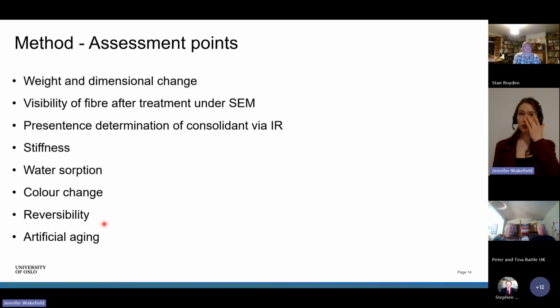Determine the presence of the consolidant using infrared spectroscopy, and then looking at the stiffness of the material. How much stiffness does it add? Does it make it noticeably stiffer? And would that make the handling easier? And then we're looking at water absorption. How does it retain humidity? Looking at the color change, the reversibility, and also artificial aging.